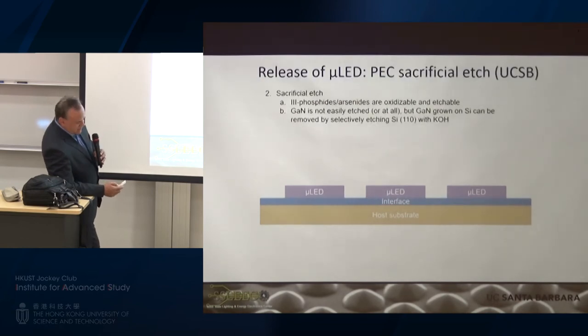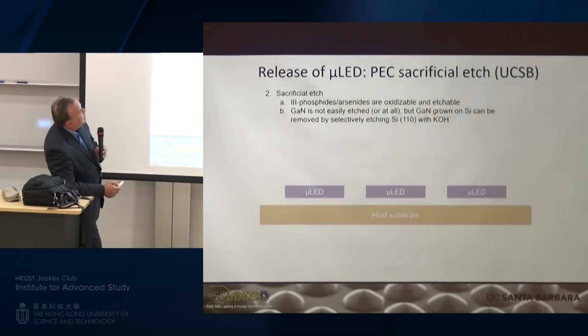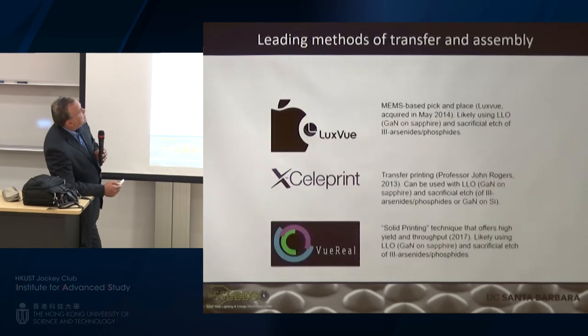So we've developed what I call a more elegant solution and a lot less damaging. That stands for PEC. This is photoelectrochemical etching. In that layer, we just put a sacrificial layer here, and we just etch it from the side, and then we're left with freestanding little micropixels. And so this is the approach that we're taking. These then could be put down by stamping. We've also put them in solution and inkjet printed them. And I'll just show you it works.